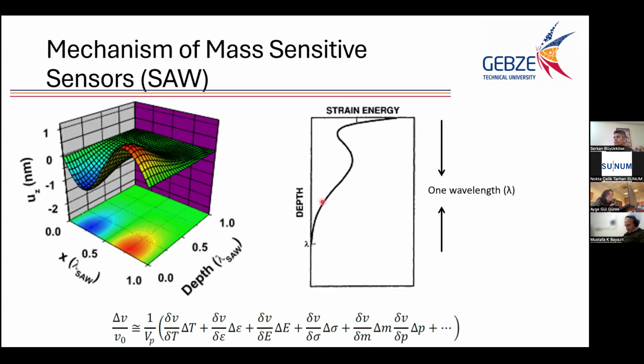So this means that if the energy is restricted to the surface, it's very sensitive to any perturbation on the surface. What kind of perturbations am I talking about? Here you see this perturbation might be temperature, electric field, conductivity, mass loading, pressure, and some other physical changes on the surface. Any kind of perturbation can be seen as a change in velocity of the acoustic wave, or a shift in frequency.